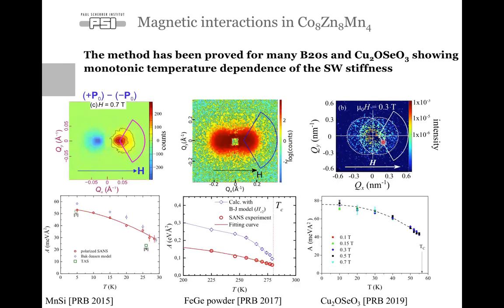Still, this technique has been applied to multiple B20 materials and copper oxoselenite, and exchange stiffness was measured very nicely for all of them. And basically all these cubic chiral materials with B20 structure and copper oxoselenite show the same behavior of the spin wave stiffness, namely it increases from TC towards low temperatures.